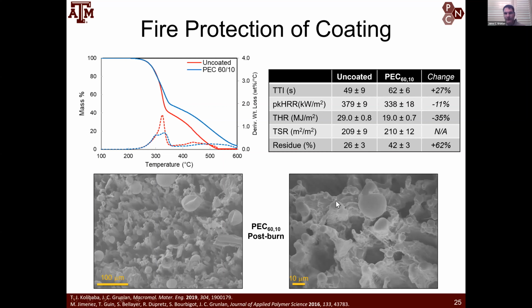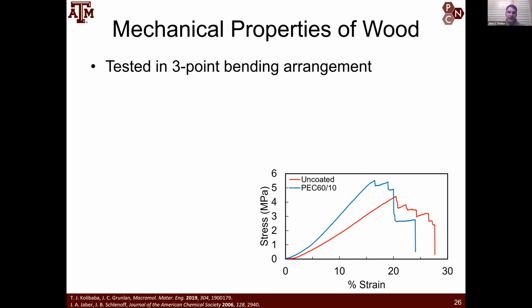And then if we look after burning on the coated wood, you can easily see this intumescent bubbling. So there is an intumescent effect going on here. Gas is released from the coating and it creates these insulating bubbles of char.